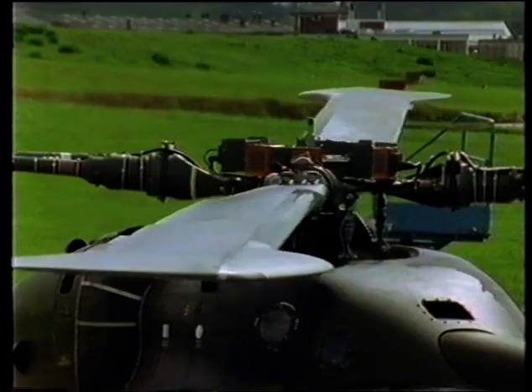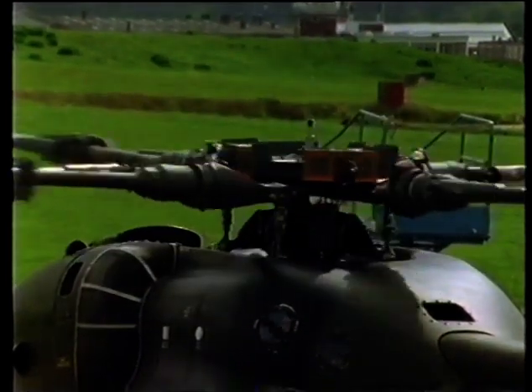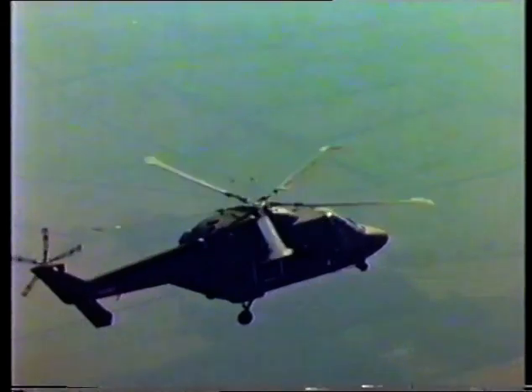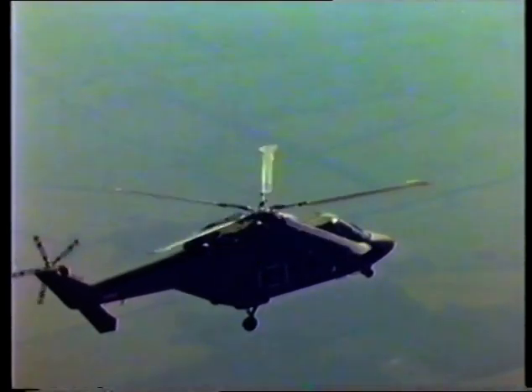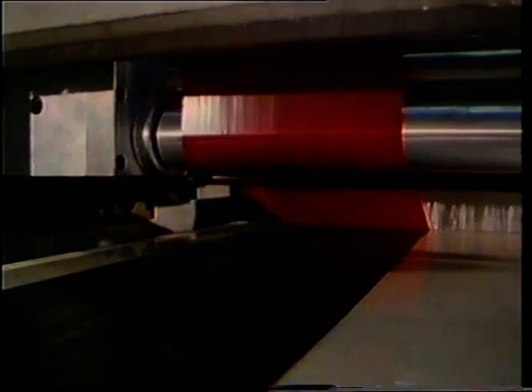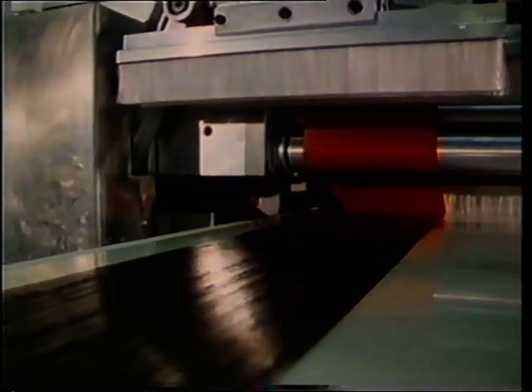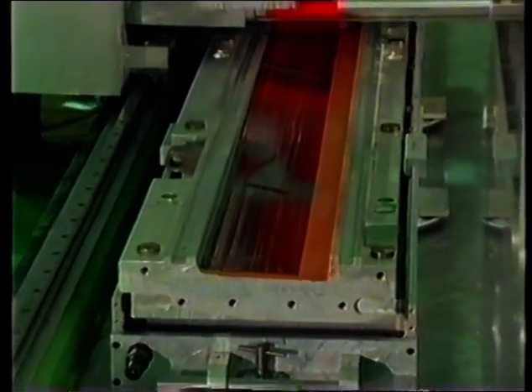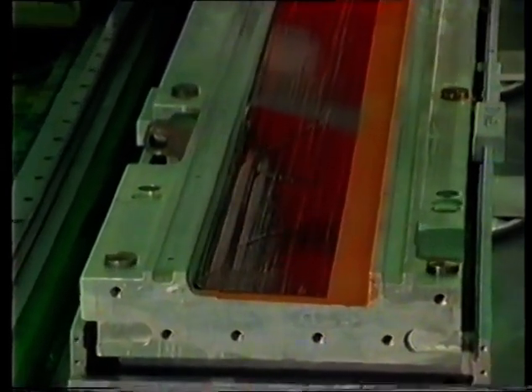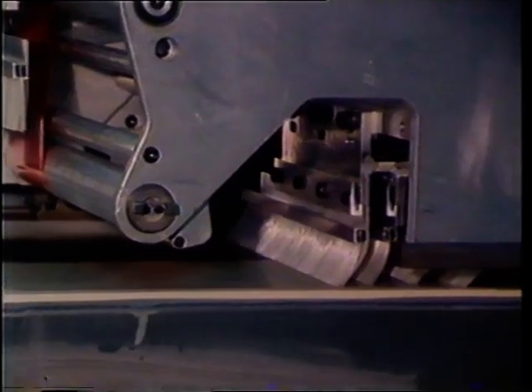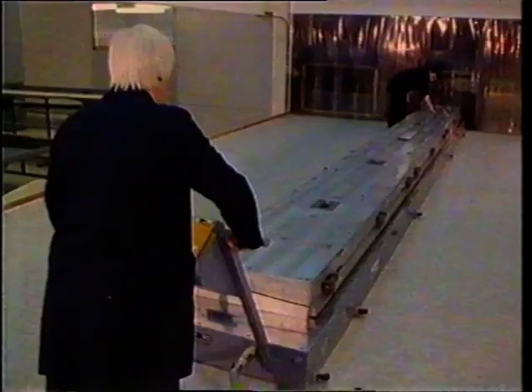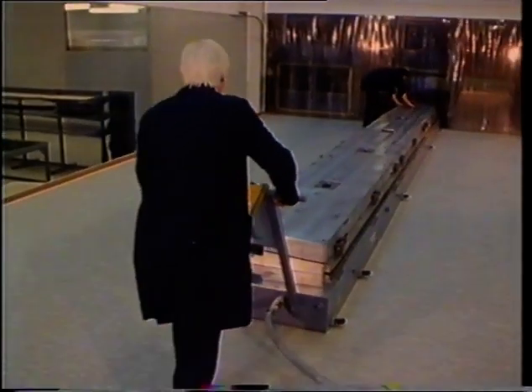Now, the main applications for carbon fibre composites these days can be found in the aerospace industry. Helicopter rotor blades, once metal, are now fabricated out of layers of composites, giving them a life free of fatigue. Within this composite sandwich, it is these carbon fibre sheets impregnated with epoxy resin that provide the crucial longitudinal stiffness. The assembled blade has to then be cured, heated in an oven, to allow the thermosetting resin to set and form the tough but flexible matrix of the final blade.